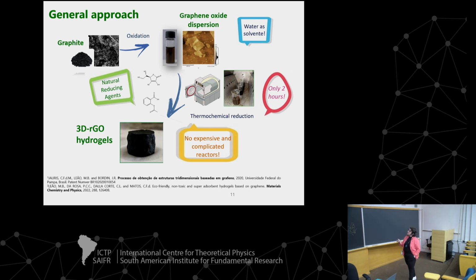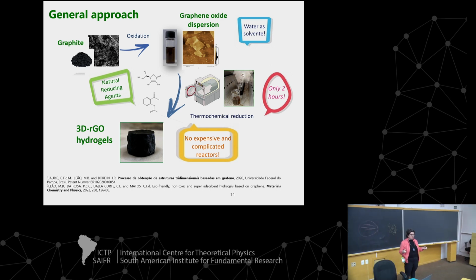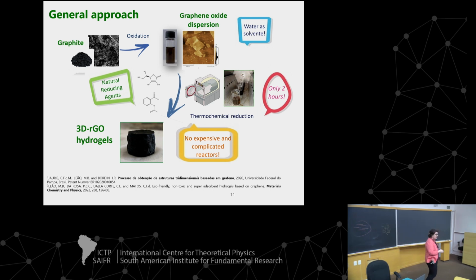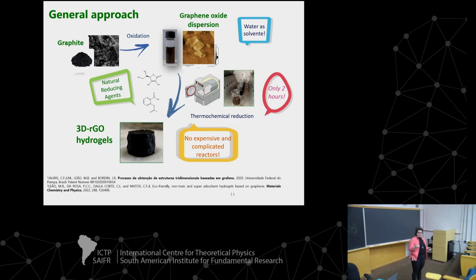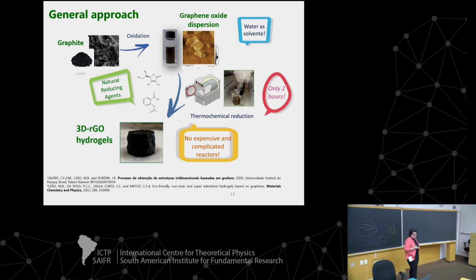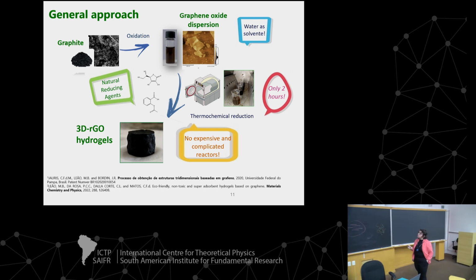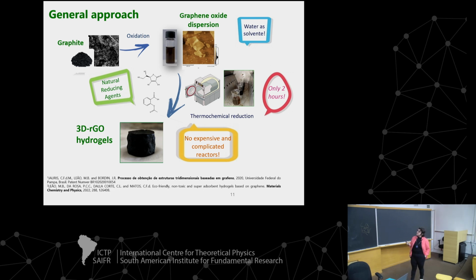We use a conventional autoclave, like the ones used in medical settings, in optics to clean glasses, and by nail makers. With this simple autoclave, in only 2 hours, using vitamin C and other reactants, natural extracts from trees, we reduce graphene oxide and transform it into 3D reduced graphene oxide hydrogels. We have this kind of material at the end of the process.